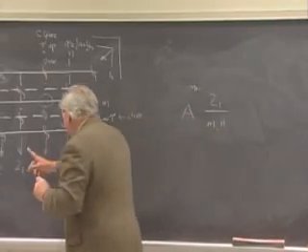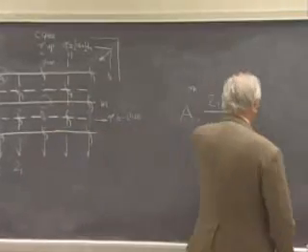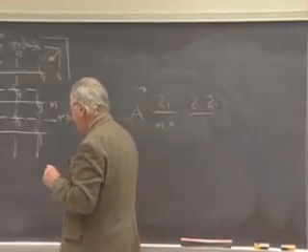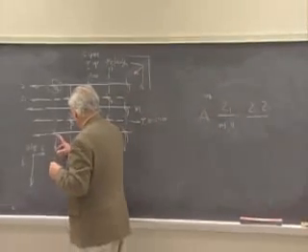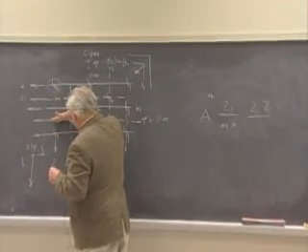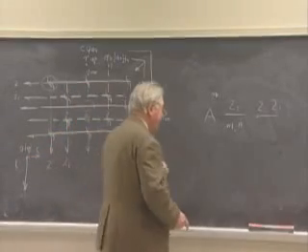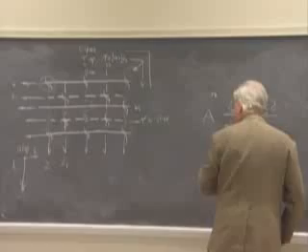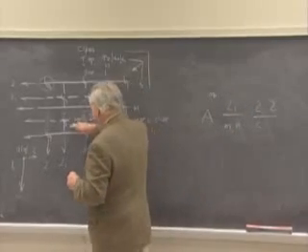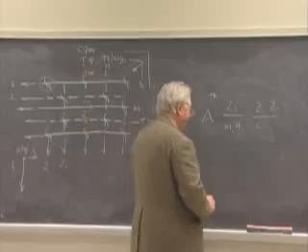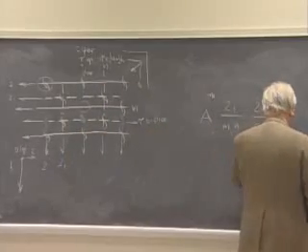If I look along B, I have the choice of either 2 or 2 sub 1, as both are present. Perpendicular to B, however, is a glide for which tau is along the direction of C. So that is a C glide. And then the other symbol for a plane that's perpendicular to B is a mirror plane. So it's either C or M.